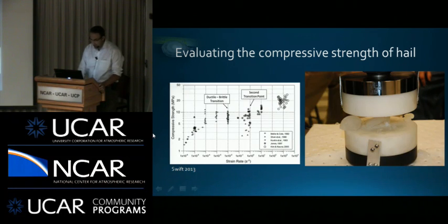This is what the strain rate versus compressive strength looks like for ice. You can see at low strain rates, we're talking about that ductile compression where the thing just compresses and holds its shape. You'll start to see an increase in the amount of load it can support, and then it levels off in this general range. Strain rate is in units of per second. So that flat, leveling-off area, where you get that ductile to brittle transition, occurs right in there. And so we want to get a brittle failure, so we have to come up with a device we can have in the field that can produce that.